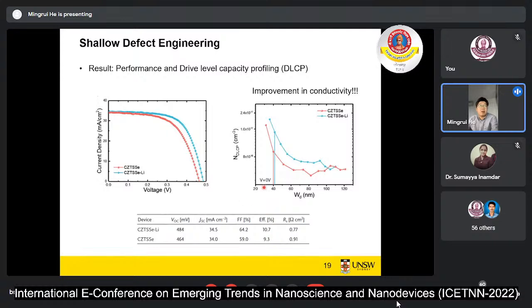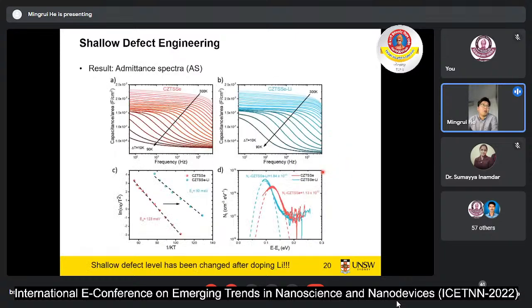After that, we characterized the conductivity of the CZTS film by DLCP. We found that the P-type conductivity has been improved after lithium doping. As you can see, it increased by almost one order of magnitude in the doping density. So here we need to know why it can be improved.